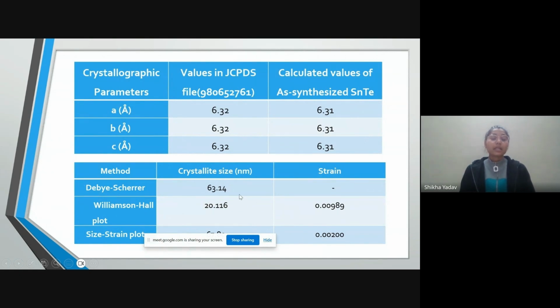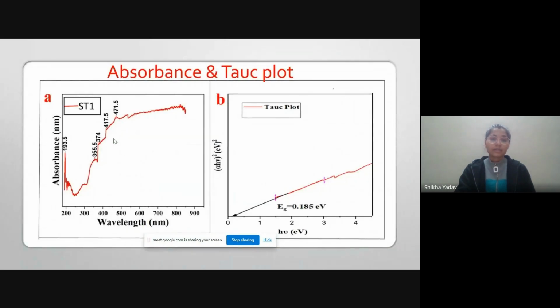Since I used three methods, now the question arises, which size should we rely on? All three methods have some advantages and some limitations too. Generally, the Debye-Scherrer equation is used to calculate the crystallite size, but it does not consider any defects in the crystal structure. Therefore, we need to use other approaches to calculate the crystallite size, that is WH and size strain, because they also calculate the strain value, that is, how much strain is included in our material. So that's why we used the WH and size strain plots to calculate the crystallite size and the strain.